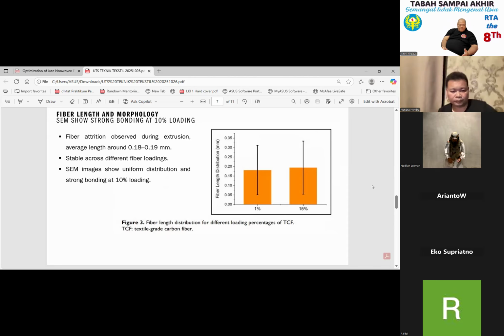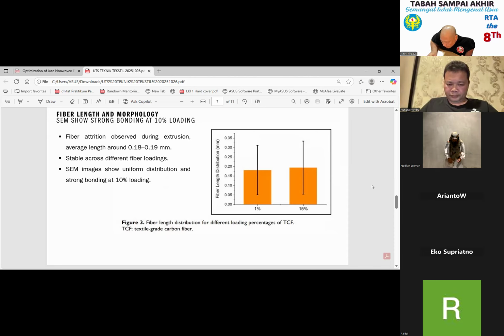That is important, because when bonding is good, the stress can be effectively transferred from the soft polymer to the stiff fiber, which results in better mechanical properties. In summary, this part confirmed that the twin screw extrusion process was effective in creating a uniform, well bonded microstructure, which is the foundation of the improved mechanical results.